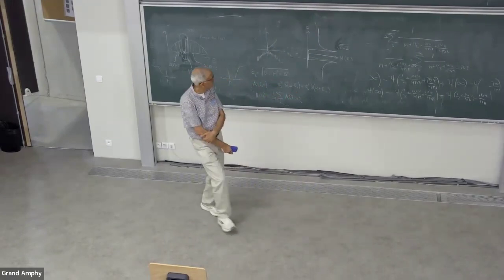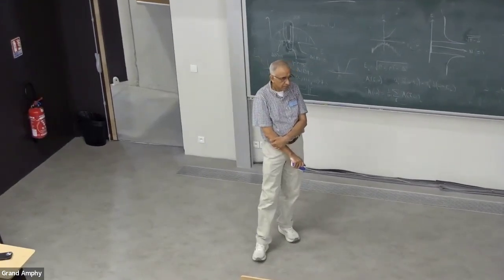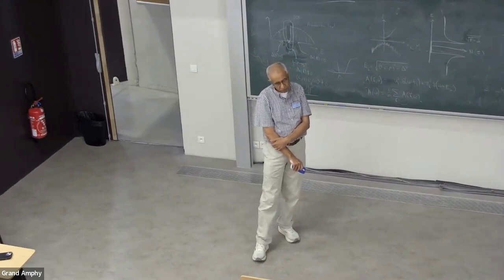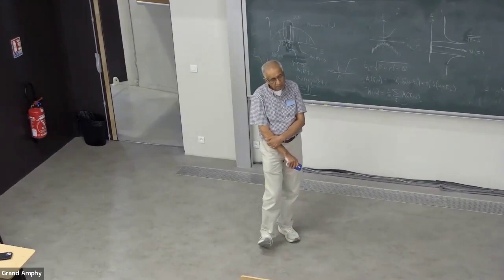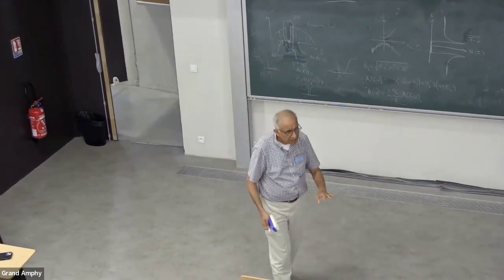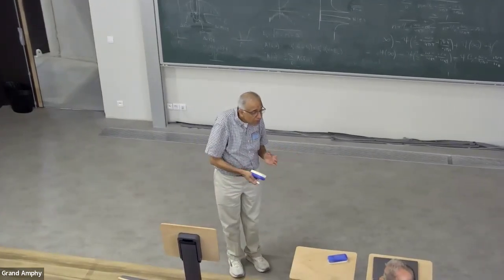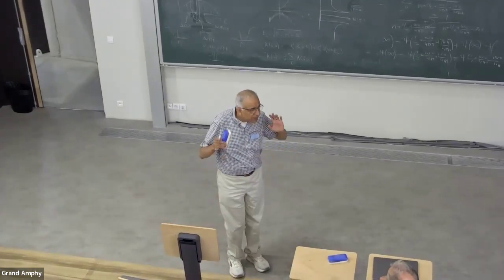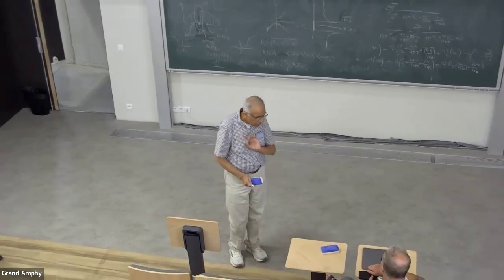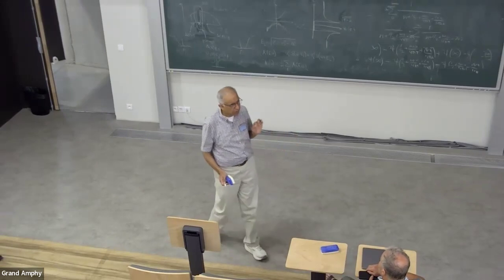Mohit, how does this Dynes parameter come about? Because we know from Anderson's theorem that it cannot be due to elastic scattering. That is exactly what I'm saying. Yes. Then they'll say there's some inelastic scattering or there's some inhomogeneity, so there's a distribution of gaps. We don't know where it comes from. It's just a phenomenological broadening parameter that experimentalists use to fit the data.